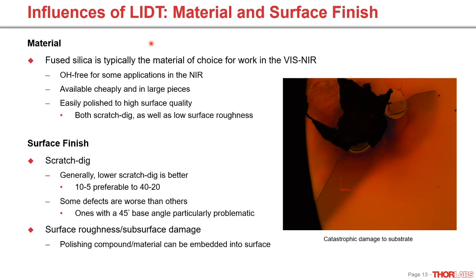As far as surface roughness, you want something with low surface roughness and little to no subsurface damage, because you want to avoid embedding polishing compound or material into the surface. A lot of those compounds are non-optical materials, or are materials with relatively high absorption at many common laser wavelengths. So again, something to avoid.